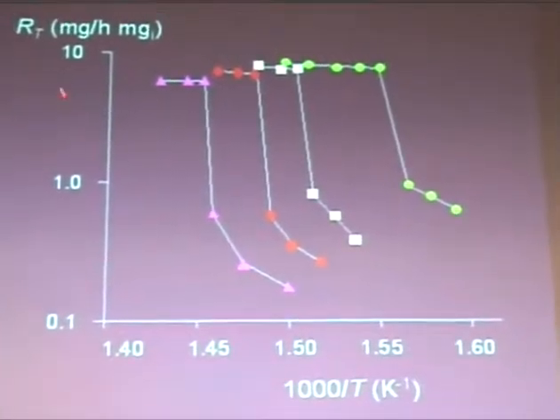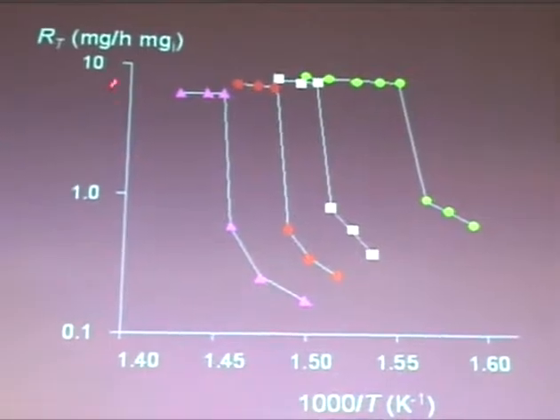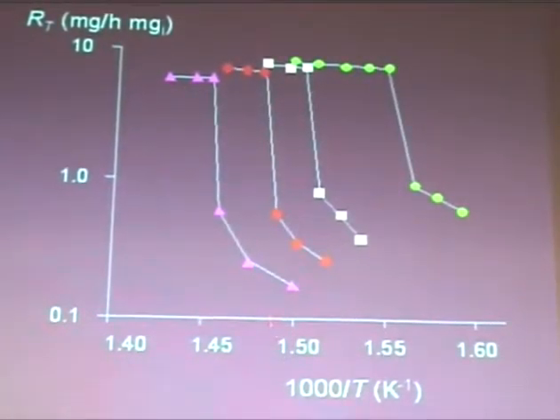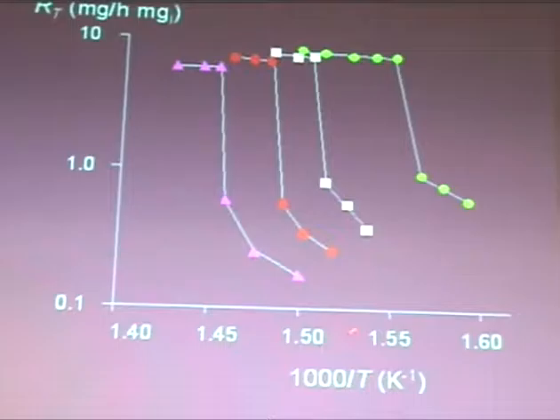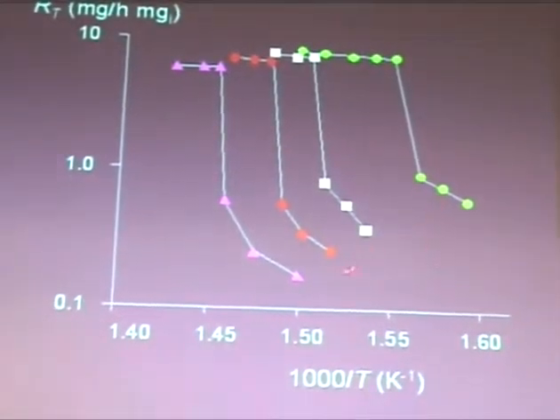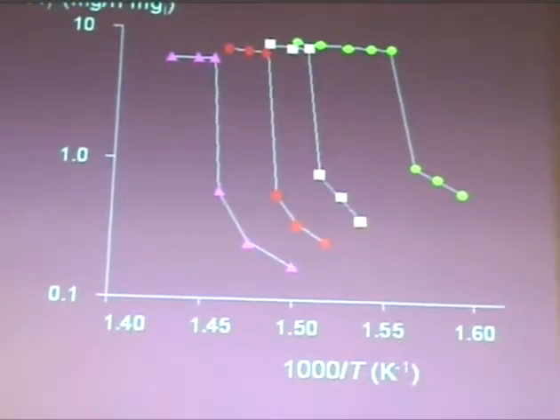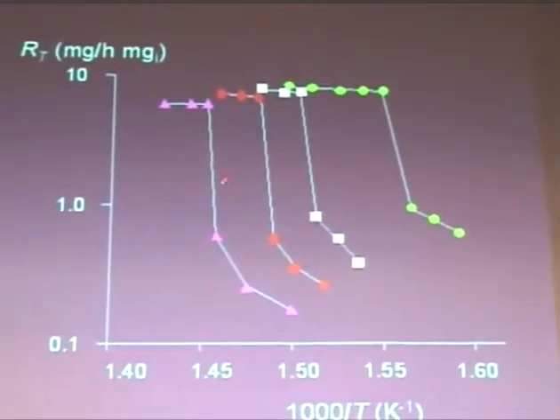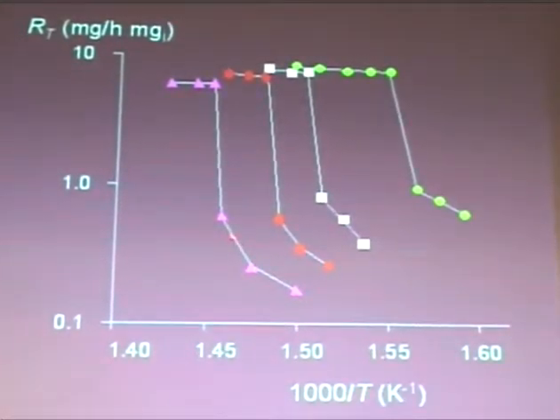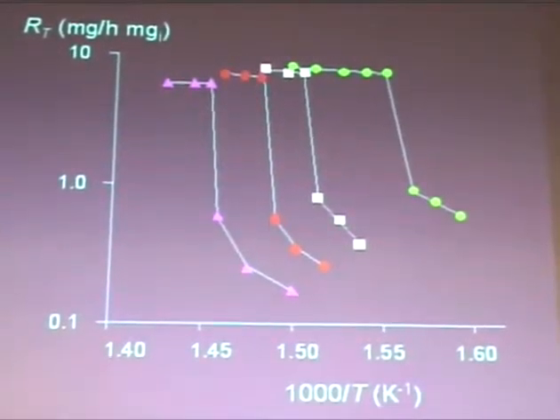This is carbon oxidation, copper catalyzed, and here's the rate plotted against the inverse temperature. So what you see here, the low temperature over here, and the temperature increases, the activity increases as you would expect. But for every curve that you see, when the activity increases, you see kind of a runaway. That's because the heat exchange with the neighborhood is not optimal, as you would expect, because it is a big packed bed, relatively, in a flowing atmosphere.